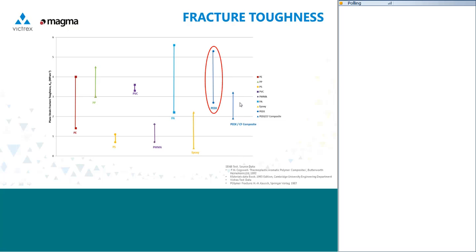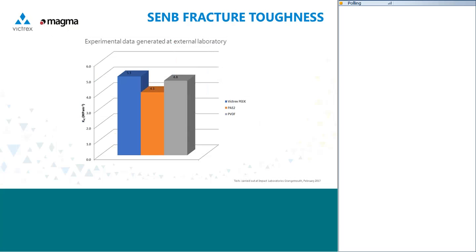What I had wanted to do in this slide was put some kind of parameters around PEEK and other commonly used pipe materials which are used in the industry. However, it is particularly difficult to find that data on the internet. So we've recently run some testing of our own: single edge notch bending fracture toughness. Single edge notch beam fracture toughness testing.